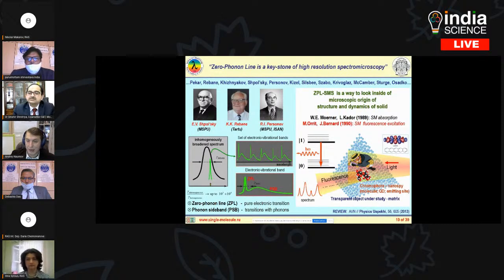in order to understand what happens in the local nanometer surrounding of the molecule. And the idea is the following. The optical spectrum of a single molecule, of some dye molecule which we put inside a transparent solid, is very, very sensitive to local surrounding, because the pure electronic transition in such a molecule depends on the state of the electronic shell of the molecule. And as a result, this spectrum is very sensitive to the state of the local surrounding. Then we can use this single molecule as a single nanospy to understand what is there.